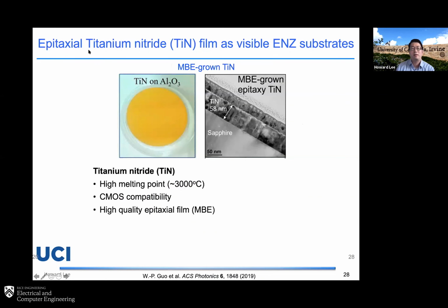So to tell you a little bit about the ENZ material we have been using, this epitaxial titanium nitride thin film as an ENZ substrate has a visible ENZ wavelength. We collaborate with a group in Taiwan. They grow it with MBE growth and can make a single crystal titanium nitride material. The properties of titanium nitride are really good: they are strong, they have a high melting point, and you can make a single crystal thin film as well. And I know Guo is also one of the pioneers making titanium nitride material.